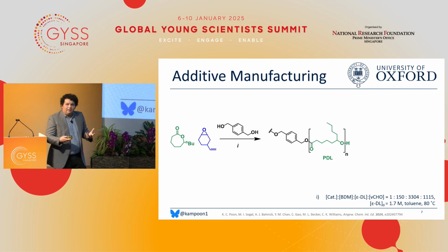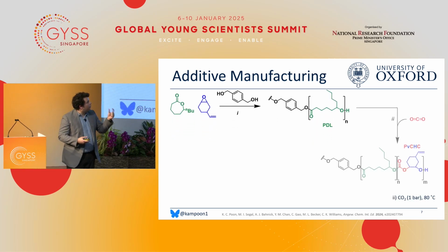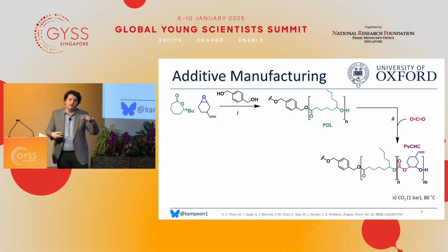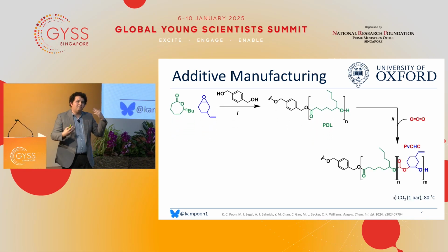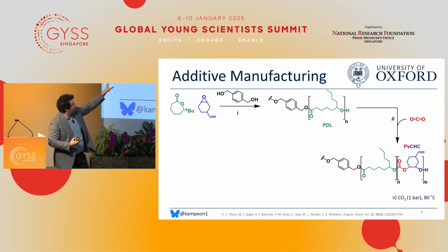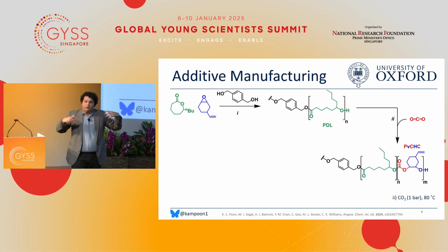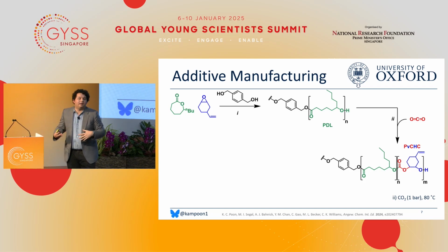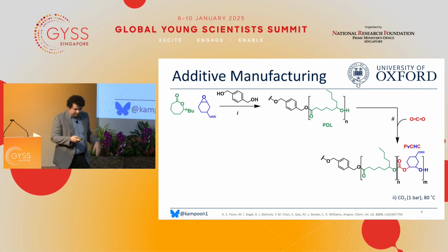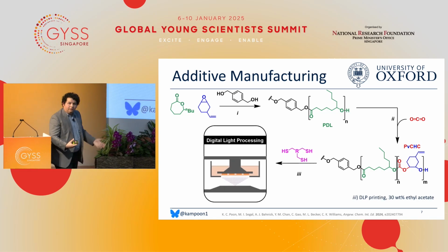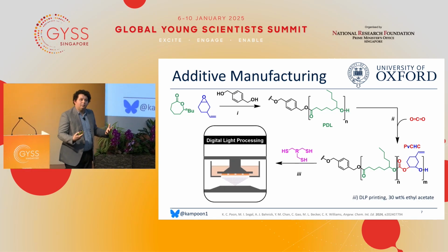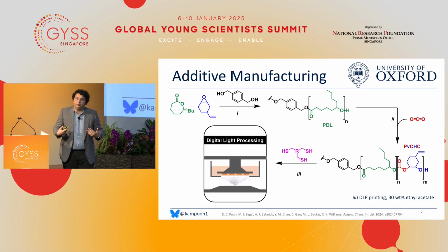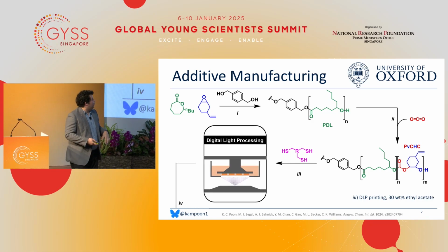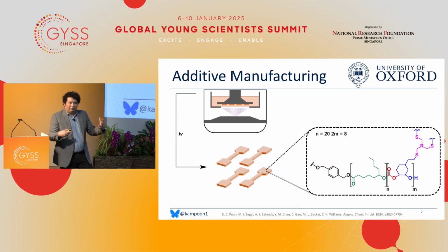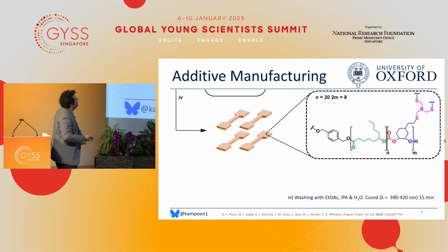And then by playing a neat little trick with the catalyst that we use, we can switch the reaction atmosphere from nitrogen to carbon dioxide and trigger a mechanistic switch within our polymerization. So we shut off the ring opening polymerization of the lactone, and we start the ring opening copolymerization of carbon dioxide and this vinyl functional epoxide. We can then exploit that double bond with a multifunctional thiol to cross-link our material and carry out our digital light processing printing.